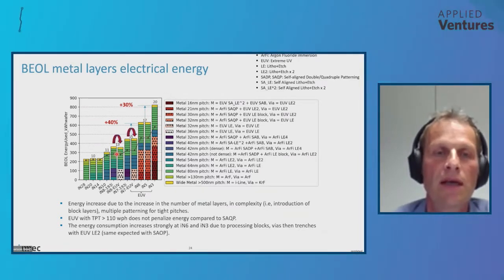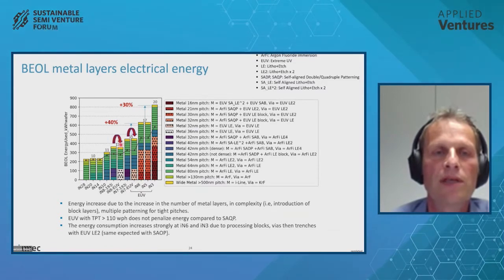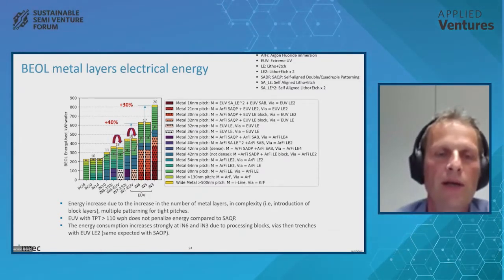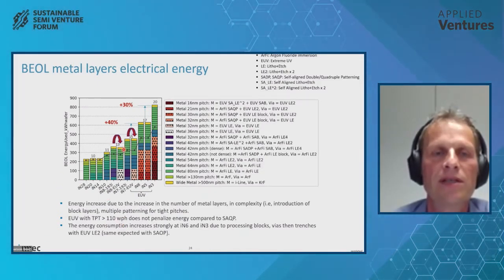We also see that if our throughput for EUV is high enough, we actually are neutral. So in this case, we have assumed 110 wafers per hour, and then we see very similar results. Now, if we assume a little bit more optimistic values, we will then see that the EUV is actually better.